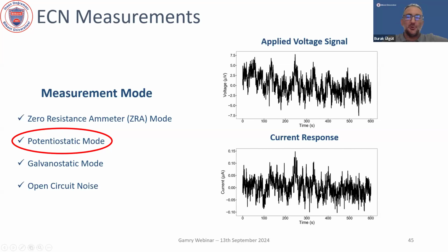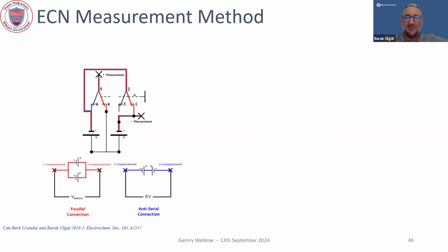So when we are doing noise measurements in batteries, we don't apply anything. We just measure the voltage. So it's not only non-invasive, it's actually non-perturbing. We just listen to the voltage. However, the voltage measurement of microvolts on top of 4 volts is super tricky. The voltage reference that's used in order to suppress the background has noise of its own, and that can confuse the hell out of you.